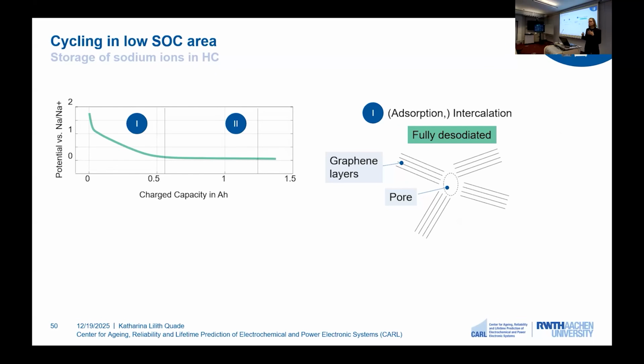However, the exact sodium storage mechanism is still the focus of ongoing research, and we are presenting a model that is highly cited in literature, consisting of two steps. Here on the right-hand side, we can see a hard carbon schematic consisting of graphene layers and also a pore. And here on the left-hand side, we can see again our anode open circuit potential curve. Just for your orientation, here the cell is fully discharged. This means that the anode is desodiated. Here the cell is fully charged. That means that our anode is sodiated.